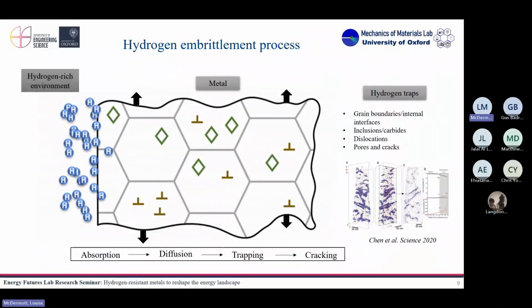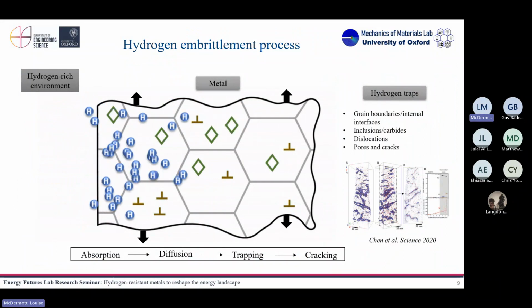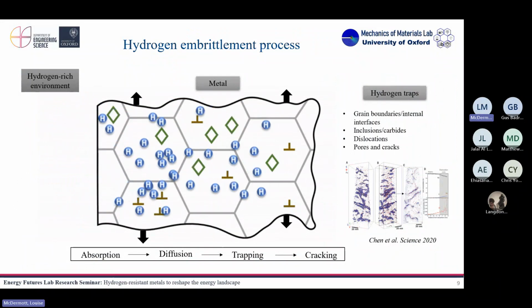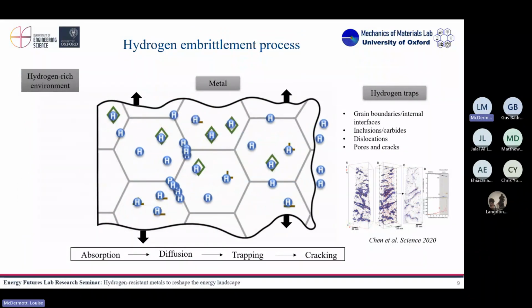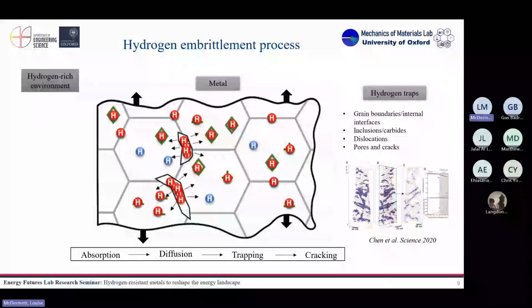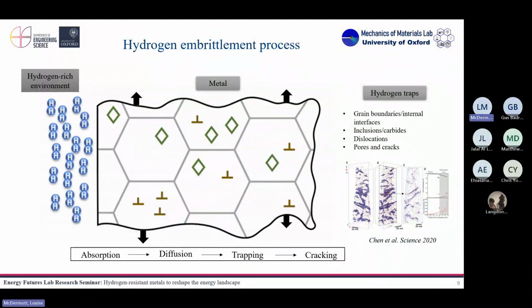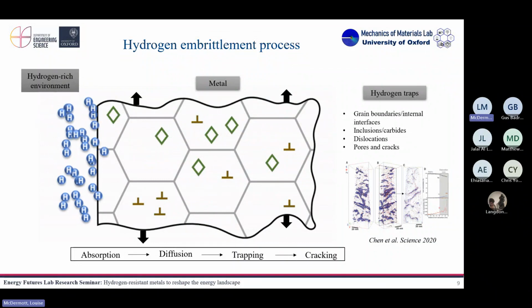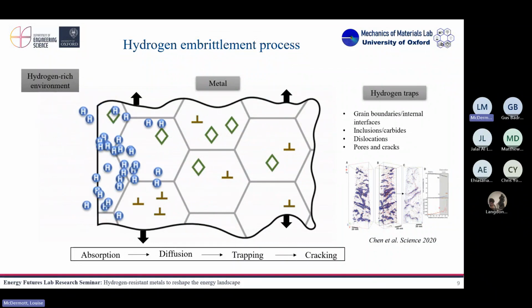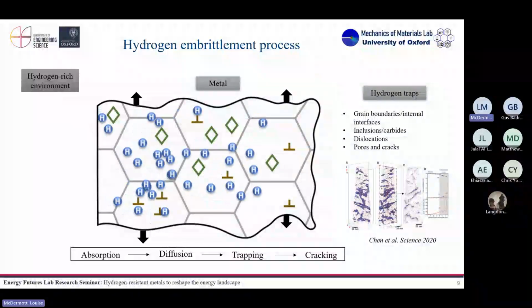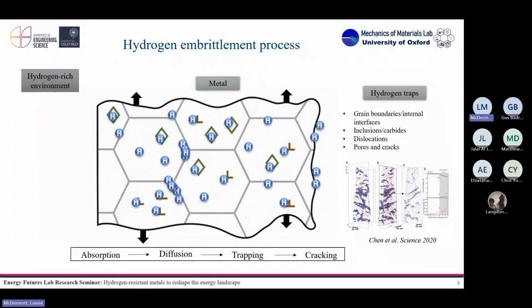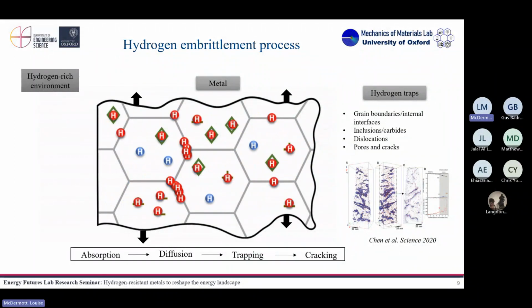So actually what really happens with hydrogen is that it can be absorbed from a hydrogen-rich environment. As I said before, it can be whatever. Let's focus on hydrogen gas, okay? One, it is absorbed. Hydrogen is so tiny that it can diffuse very easily in the lattice of your metal, through the interstitial lattice sites, and it can get trapped in defects during this lattice diffusion.